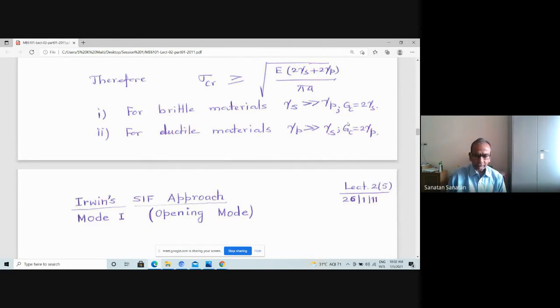Now, coming to the other objections or shortcomings that people raised: it considers the crack to be loaded normally, about its own plane, but it can be different. So we must answer that question. And similarly, it is just one loading. The loading is perpendicular to the crack plane. But if it is different, let's say shear loading, or at an angle, those are the problems which couldn't be answered by the theory that was propounded by Griffith initially. So again, it became a problem.